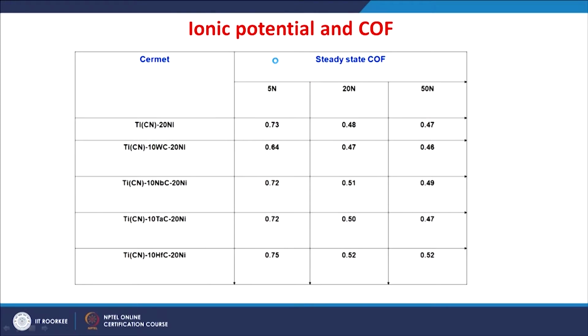So, these were actually tabulated, the average steady state coefficient of friction for the investigated cermets for the different loading conditions. You can see higher coefficients of friction are obtained at the lower loads, whereas this decreased at higher loads of 20 or 50. The average steady state coefficient of friction is between 0.64 to 0.75 at 5 Newton for the investigated cermets, whereas at higher loads of 20 or 50 Newton it varies from around 0.46 to a maximum of 0.52, but there is not much difference in the friction obtained at higher loads of 20 or 50 Newton.